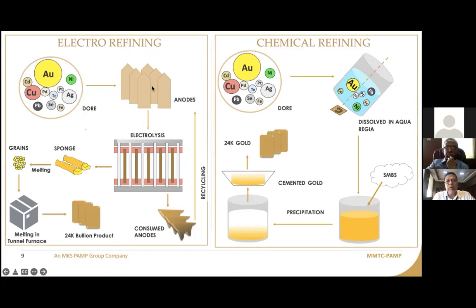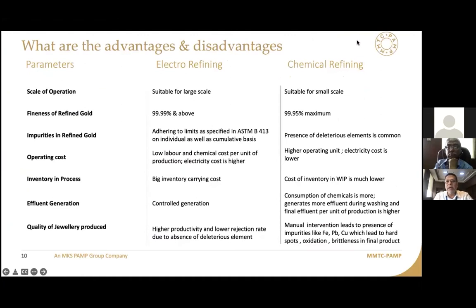You have the doré, you make the anodes, you go through the electrolysis setup of anode and cathode, where the impure anode gets dissolved into the solution and pure gold ions get deposited onto the cathode. The consumed anodes are remelted and made back into anodes. And the sponge which you get, which is, I would say, 4N9 plus and devoid of any impurities, is melted into grains, which are then melted in a furnace to make bars. So this is the basic thing which is required. What is the basic difference? Electrolytic refining you can do on a large scale. Chemical refining also you can do on a large scale, but normally people set up small scale units, 5 kgs, 10 kgs, 50 kgs.